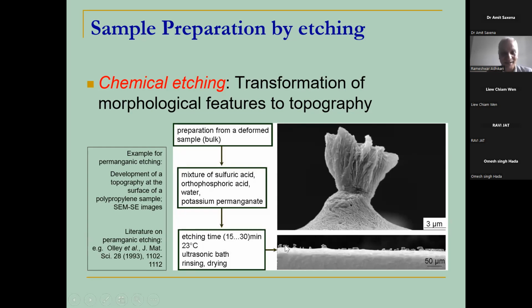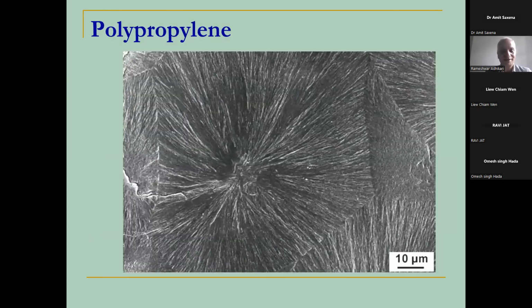on the surface, and the etching did remove the amorphous, more loose part of the surface, and the crystalline part was there. And this is the typical structure of so-called polypropylene spherulite. So if we take a very brief etching on a polypropylene sample surface, then we see these spherulite structures. This is the boundary between the spherulites. So this is one region which is not very well crystallized. So these are the radiating lamellar structures of polypropylene.